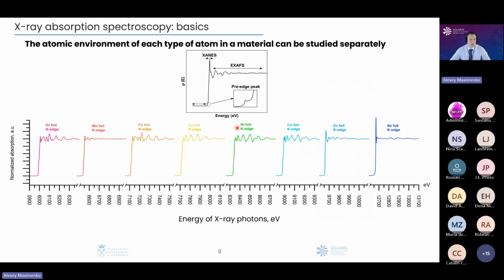Okay, what is also very important when we speak about X-ray absorption spectroscopy: each atom has an absorption coefficient at a very defined energy range of the photons with which we irradiate our material. Here, for example, you could see a set of different absorption edges of 3d metals, and you could see that they are separated in energy. And it means that when we have a very complicated material which consists of different elements, we could precisely focus on one element, and, as we will discuss in the slides further, from these spectra we could get information about the atomic environment. And since all of these absorption edges of elements are separated from each other, we could investigate the atomic environment of each type of atom individually, even if the material contains quite a large amount of different atoms.